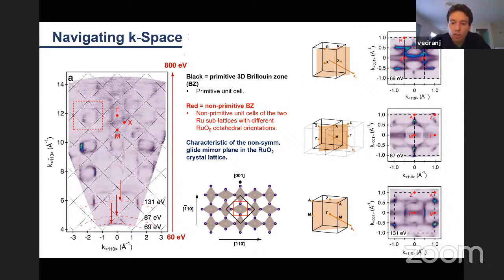And then in contrast, at 87 electron volts, the middle one on the right, and at 131, you are probing the 3D Brillouin zone close to the 110 plane, identical with this GMAZ high symmetry plane, with either the AM or the GZ lines centered in the ARPES map, as I will show you in the upcoming slides.